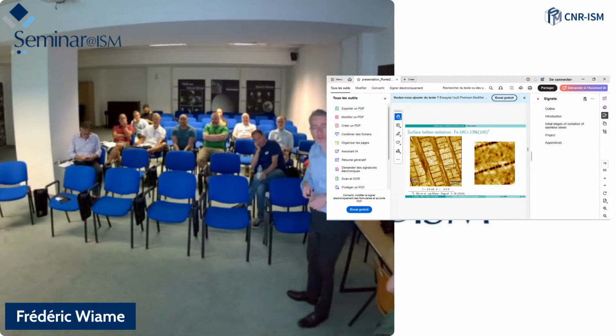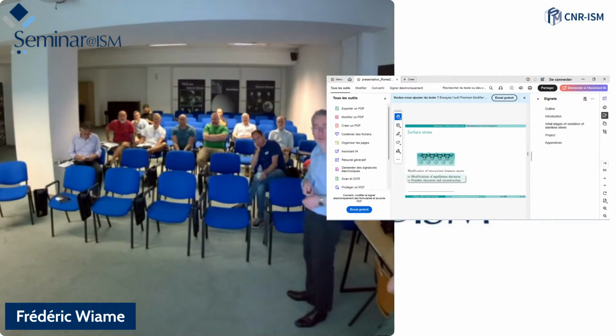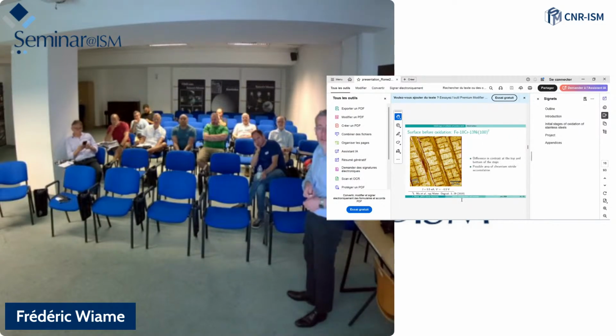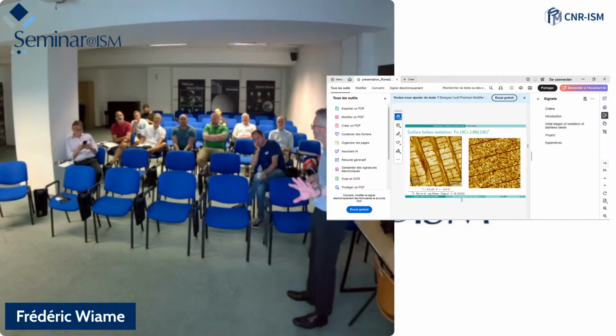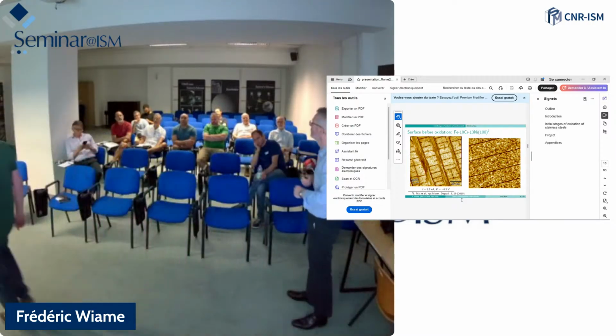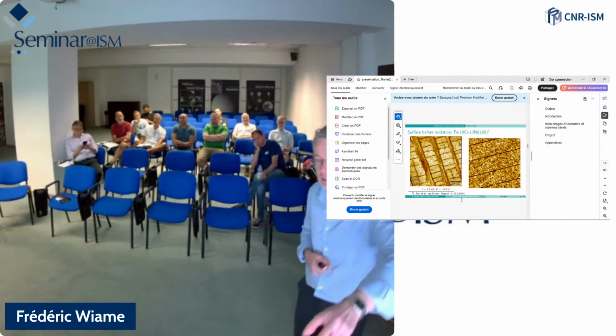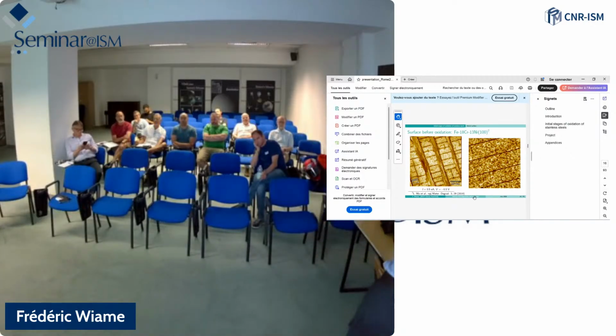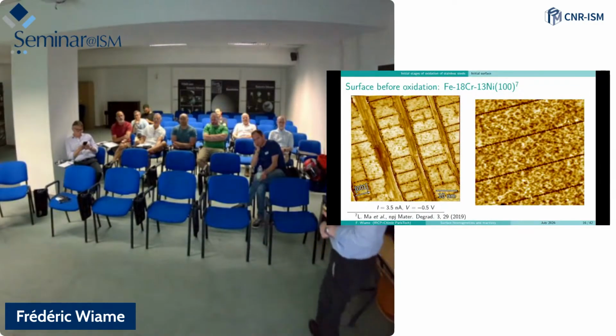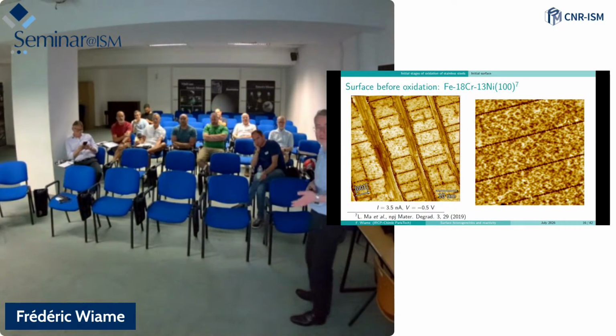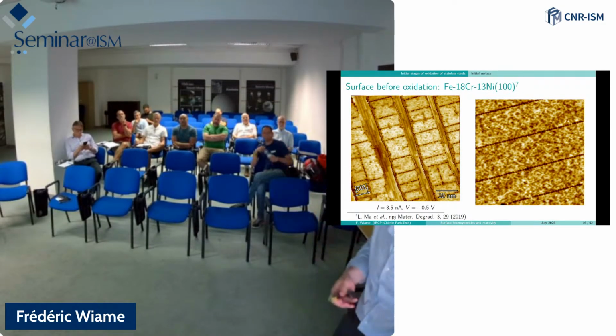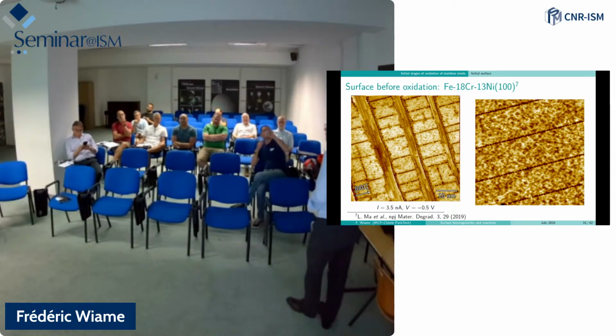This is what we can see on this image. The contrast that you can see is really due to the fact that we have iron, chromium, and nickel at the surface. So this contrast here is due to the fact that we have different elements at the surface. On this surface, we should have something like 12% of chromium, 9% of nickel, something like that. Which is less chromium and nickel, and we have also nitrogen here. So this is less chromium and nickel than in the bulk, but we still have the different elements at the surface.